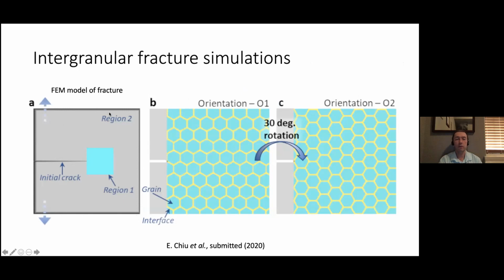And we applied a far field tensile strain on this model by applying tractions at the end of this sort of large region 2, which was coarsely meshed so as to conserve computational resources. And then on the inside, we had region 1, which was more finely meshed. And if you zoom in and see what it looks like, we actually made it so that it was made up of a microstructure, a tiling of hexagonal grains. And so you can orient a tiling of hexagonal grains in different ways. We had orientation 1, which is the one that you see here in the middle. We also had a different orientation, orientation 2, which was a 30-degree rotation of the one on the left. And we investigated, how does the crack run through these microstructures?